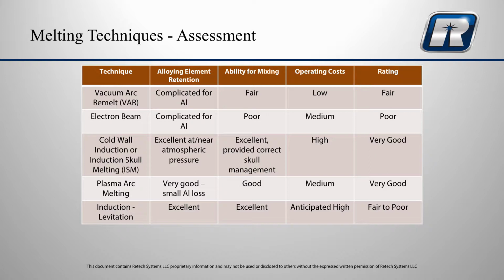We looked at vacuum arc remelt, electron beam, cold wall induction, or some people will say induction skull melting, plasma arc melting, and some of what we call the newer techniques, induction levitation. So with regard to alloying retention, as you see here, we kind of rated each one. The vacuum arc remelt is somewhat complicated for aluminum. Electron beam, of course, is also complicated for aluminum due to the high vapor pressure, or relatively high vapor pressure, of aluminum. Cold wall induction melting actually can be quite effective for melting the titanium aluminides, because in many cases you can backfill the chamber and melt at atmospheric pressure.